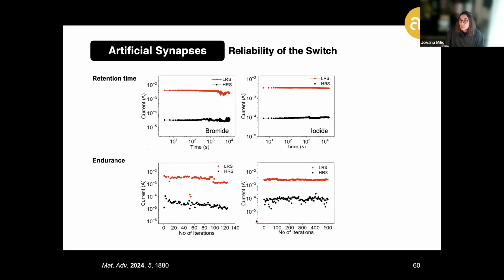We can see for both the bromide and the iodide counterions a distinct distinction between these two states, being the low and high resistance states, with an on-off ratio of around 10 to the 2, and a retention time for each of these states in the order of around 10 to the 4 in both cases.